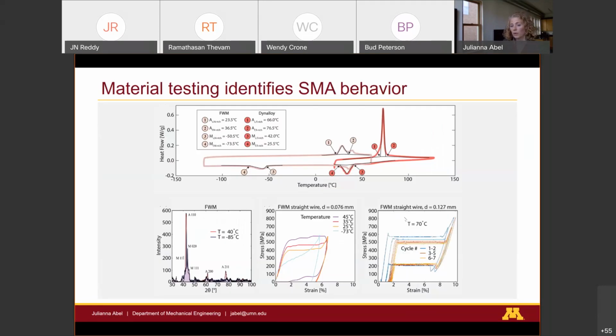And so, but what we really want to do is we want to be able to operate these on the human body. And using that Dynalloy material that requires a heat gun is not feasible to put on the human body. So we work with Fort Wayne Metals to get a material that worked for us. And so this material, instead of having a very high transformation austenite finish temperature of 76 degrees that we saw on the wire, the NiTi number 4 we got from Fort Wayne Metals had an austenite transformation temperature of 36.5. And so that is within safe realm to operate on the body, because you can go up to maybe 45 degrees without causing burns.